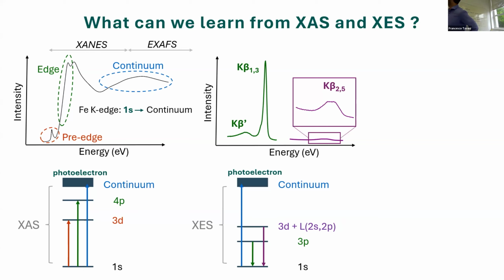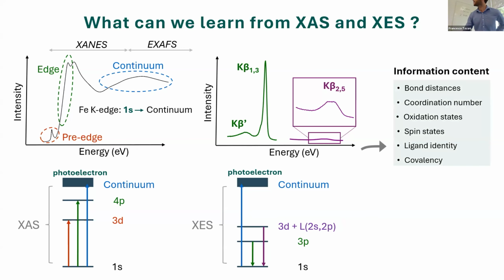What can we learn from it? We can learn, for example, that the shape, the intensity and the energy positions of these peaks are very sensitive to the ligands around the given photoabsorber. Of course, you need a model to interpret this. So for example, as I mentioned before, we can get the bond distances, the coordination number, the oxidation state, spin states, ligand identity, and also obtain from XES, especially, information on the covalency of our system.